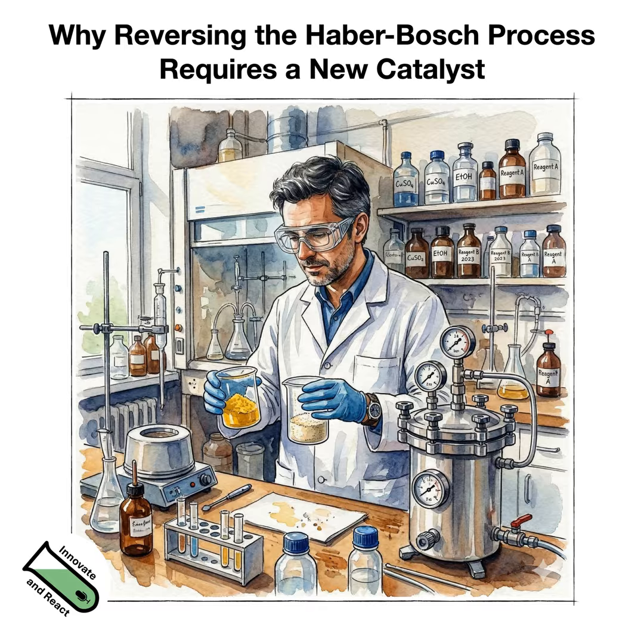Yeah, I think it's not orders of magnitude less active, but it is less active. So it's not a substitution for ruthenium. But what we could do with this catalyst, and of course you can look at activity from different perspectives. In academia, typically we are interested in the activity per active site or per surface metal. And there ruthenium, I think, is still unbeaten. But what we can easily do with those cheaper and more abundant metals is... Yeah, it should be orders of magnitude cheaper, right? Yes. And we can increase the loading.